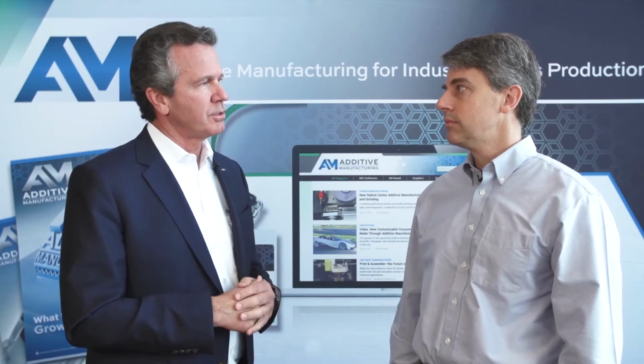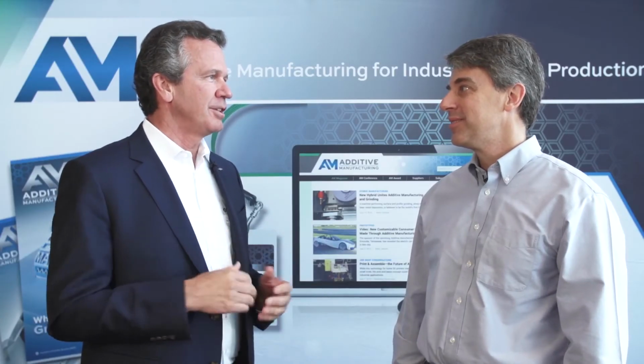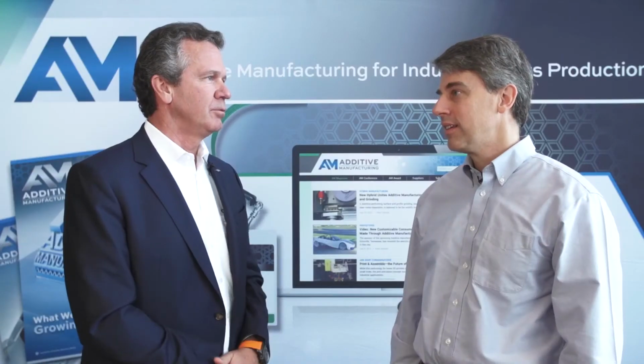We had one of our large aerospace customers do a rather extensive test. They were worried about bringing an M2 in and the environmental health and safety issues. So they put a sensor on the person's collar, one on his waist, one at the receiving station, and one at the entry door. And they ran a number of alloys. They ran the light alloys, aluminum for a while, then they switched to Inconel. And then they checked all these sensors. There was a bit of drama, right? What's going to be in there? They didn't find a trace of any powders or any soot or anything in any of these sensors. And that gave them tremendous confidence that this process and the architecture that Frank has created is truly safe and can be run effectively and safely.